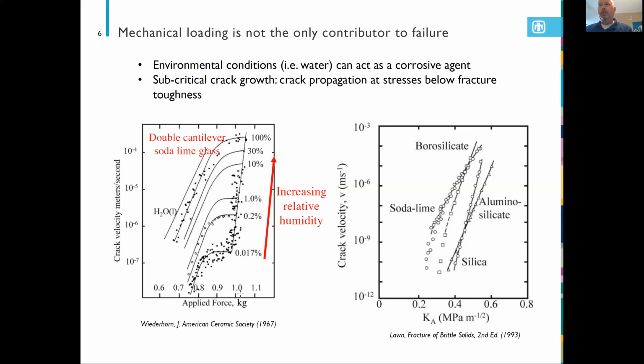What we've later started to understand is the fact that the presence of water can actually drop the energetic barrier of a silicon-oxygen bond by a factor of 5. And so that's quite significant in the case where surviving long duration environmental conditions is what you're shooting for with glasses. I must note that it's not just soda-lime glass that exhibits this property. There are a multitude of silicate glasses with different contributions from different ions that ultimately exhibit this slow crack growth or subcritical type crack growth.